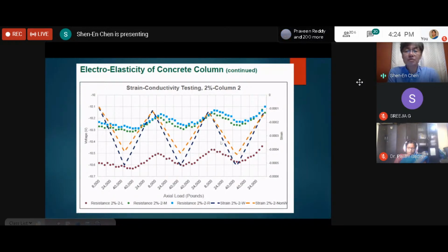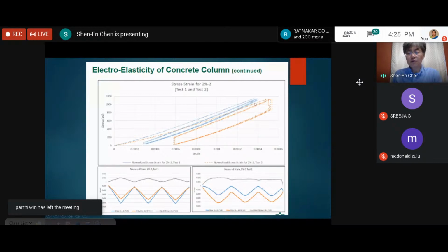So as I mentioned, because we are using AC current, you can see the single phase response. In this case, you will use the average values of the voltage change as your reading. And this is the outcome from a 2% column. And we do cyclic loading so that we can ensure that our readings are consistent and repeatable. So you can see that we load this beam in a cyclic manner for 3 cycles. Loading, unloading, and then loading, unloading again. And so for the 3 cycles, you can see the change in strain, which is read by the attached strain gauge, and then by the resistance or the voltage measurements.